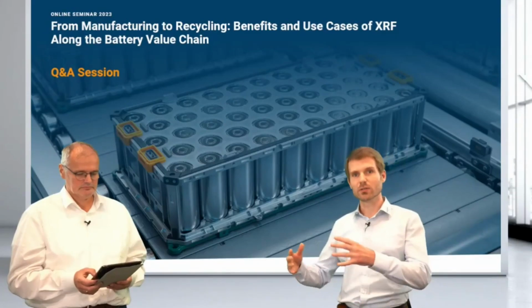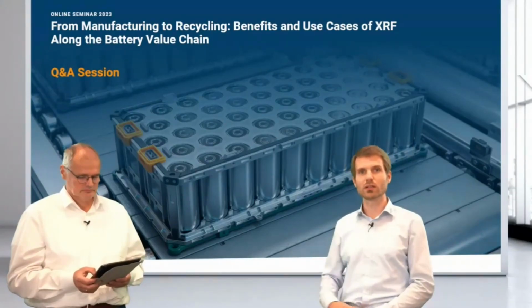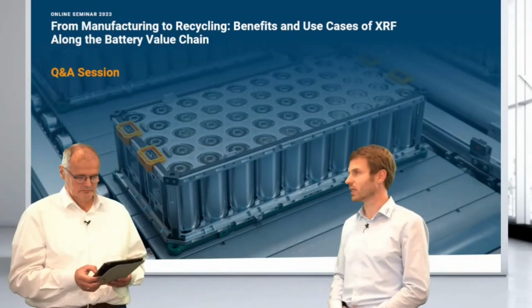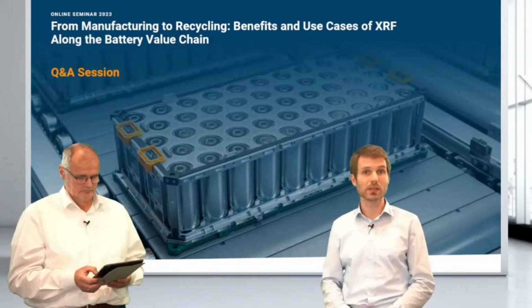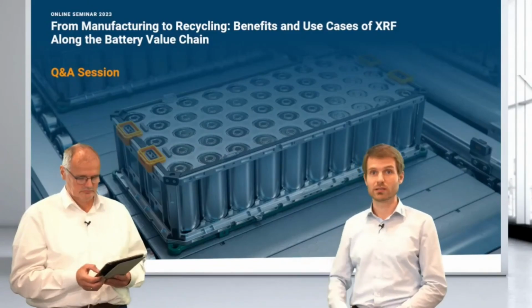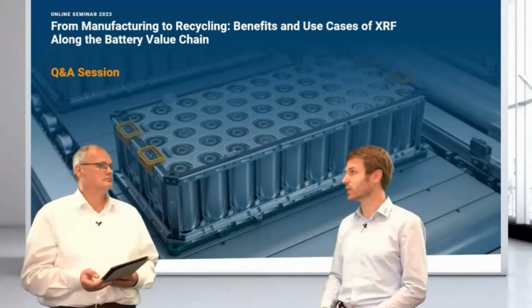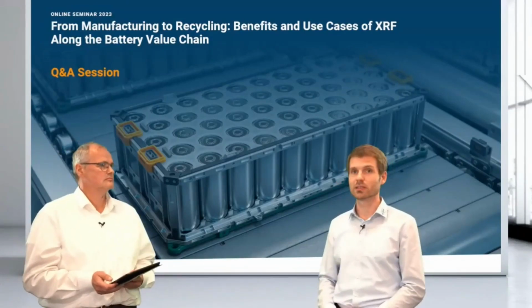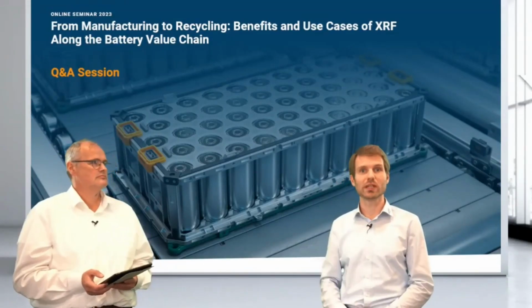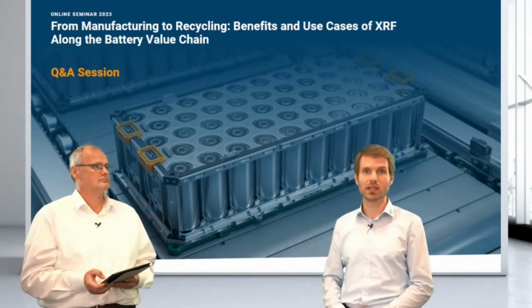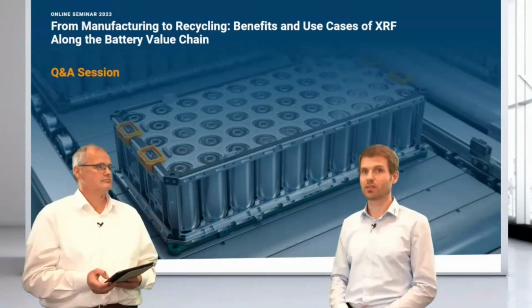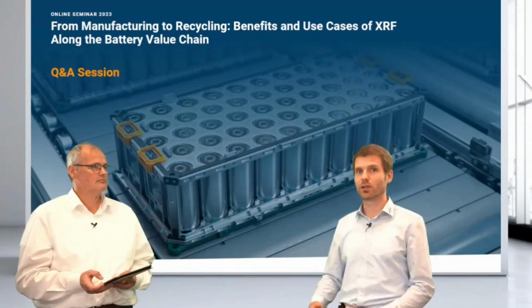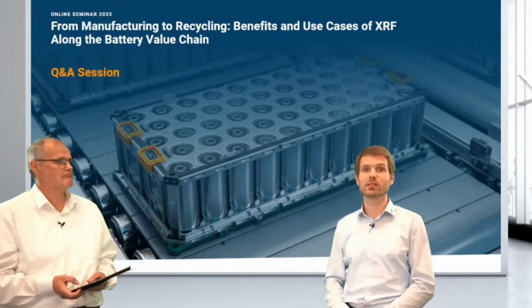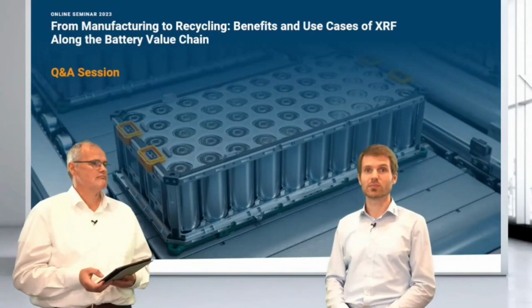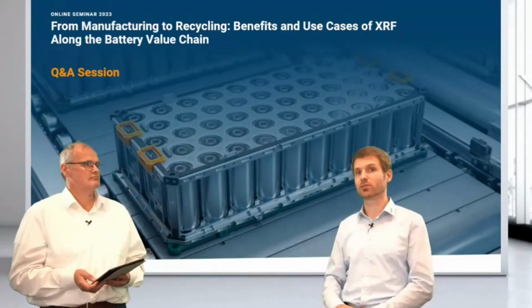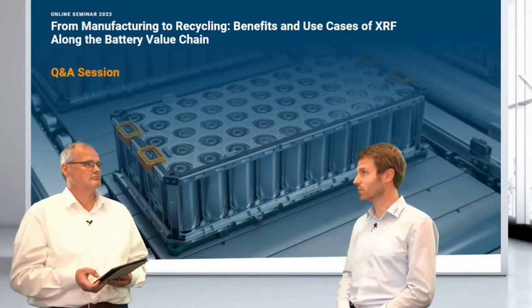Of course, when you go to real low concentrations, especially of light elements, like a few ppm of sodium or low concentrations of fluorine, that's when you reach the limits at some point, or some traces that are really sub-ppm or ppb level. This is then something you have to do with ICP at some point. But for the majority of the applications that we see in elemental analysis, especially along the production process and in the recycling process, XRF has really a number of advantages.